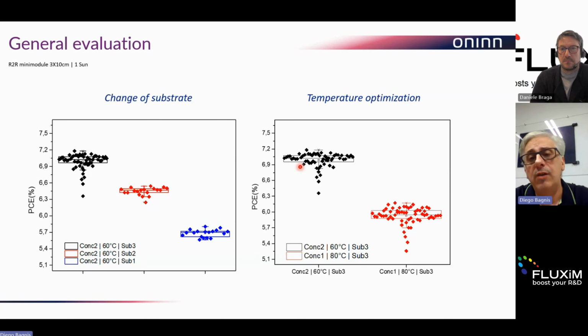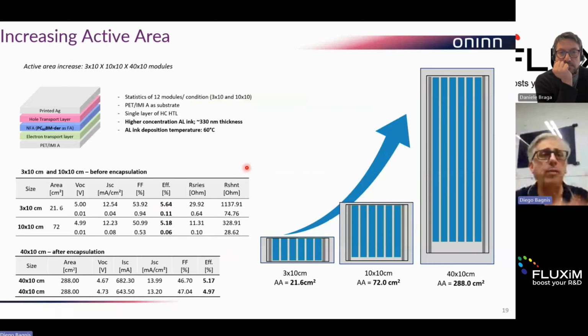Just to underline the point, the great results are a combination of several parameters, and not only the parameters of the process, but also the material and the supplier that you are using. If we try to take one step forward, especially to increase the area, we can see that, for example, before the encapsulation in the 3x10 and 10x10 modules, the performance clearly starts to drop slightly.